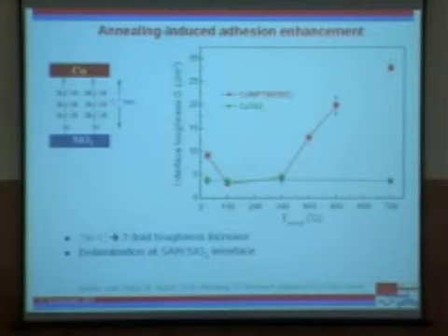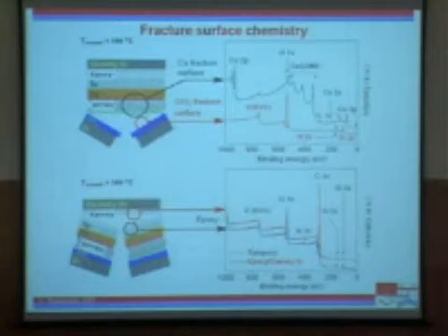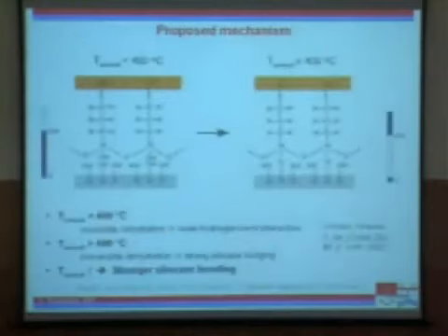All right? So what's going on? I mean, this is totally counterintuitive, because these molecules are organic molecules, and normally people study these on surfaces, and these desorb, and above 300 they're not even considered for any use. But this suggests that we can use these at high enough temperatures if we can use them at interfaces as opposed to surfaces. And let me just tell you what's happening, and I'll just show you the modeling calculation and spare you the experimental part.